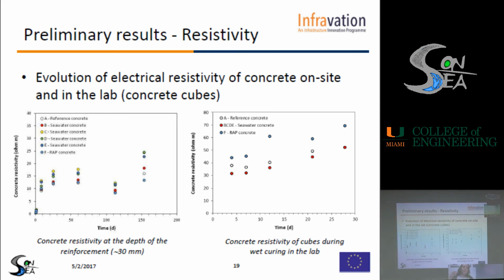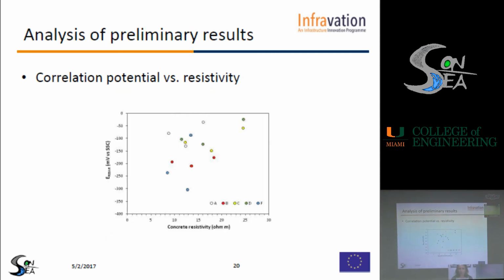However, we should consider that on-site, of course, there may be the penetration of chloride, although it is unlikely that chlorides have penetrated the concrete up to the depth of the reinforcement, that is 30 millimeters. There may be also other factors that can affect the resistivity, like, for instance, the local conditions of humidity, the temperature, and so on. And in fact, when we measure the resistivity in the laboratory on the cubes, we obtained that the resistivity of seawater concrete was always lower compared to the resistivity of reference concrete. Of course, also these parameters need to be monitored for longer periods of time in order to be better interpreted.